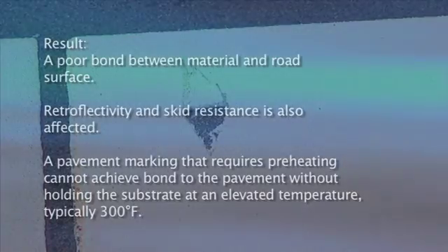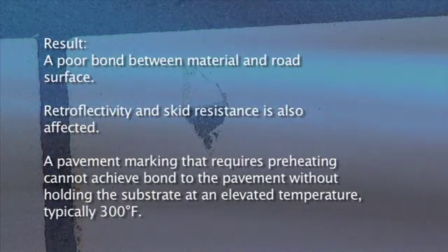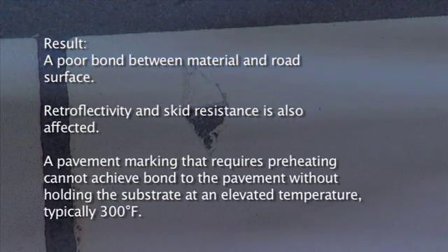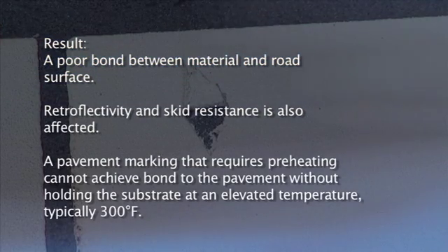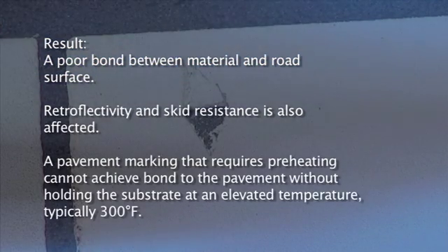A small V is created in the material and pulled back for inspection. As shown here, the result is certain to be a poor bond between the material and road surface. Retroreflectivity and skid resistance is also affected. The fact is, a pavement marking that actually requires preheating cannot achieve bond to the pavement without holding the substrate at an elevated temperature, typically 300 degrees Fahrenheit.